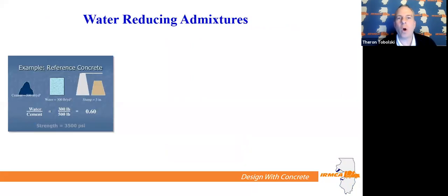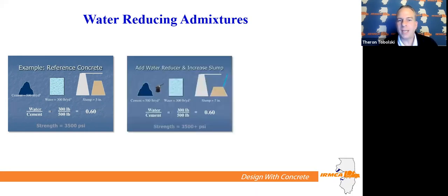Another way to explain water reducing admixtures: if we took a mix with 500 pounds of cement and 300 pounds of water, we would end up with like a 5-inch slump. If we took that same mix and we added a water reducer to it, we would end up with a 7-inch slump, and we'd still be at that same 3,500 PSI concrete mix. So all we did is add a water reducer and we gained 2 inches in slump.